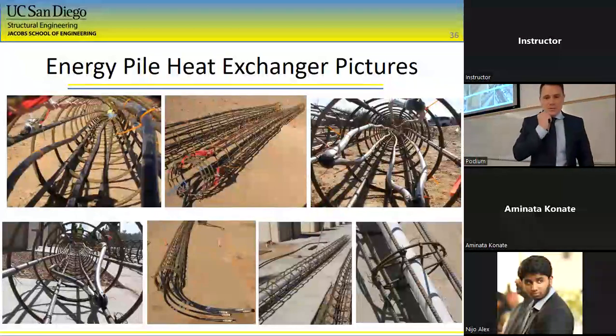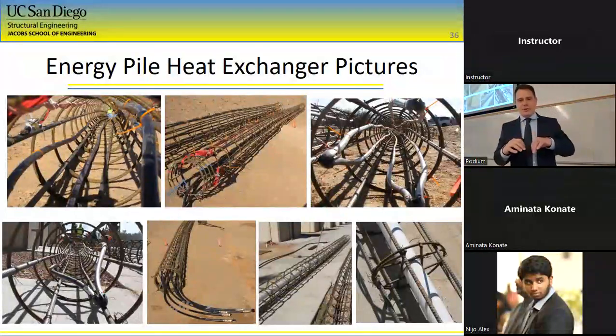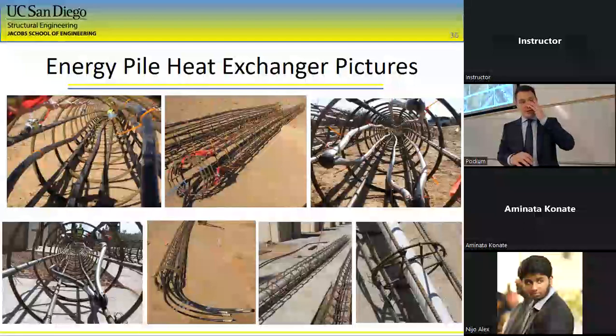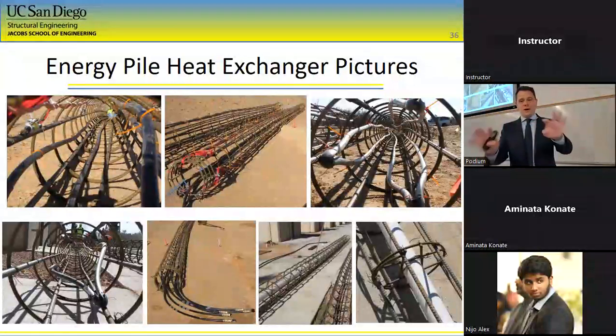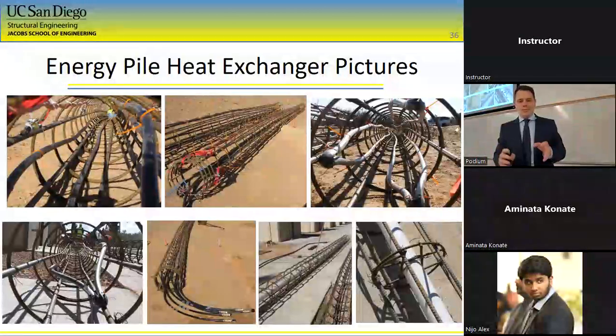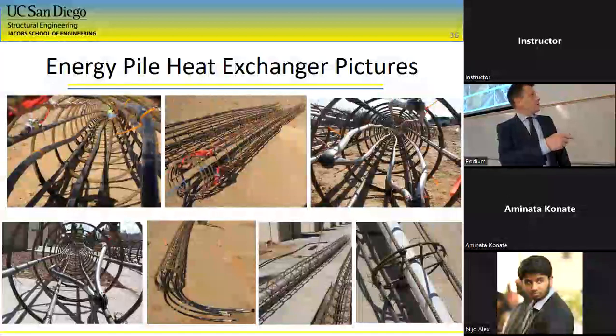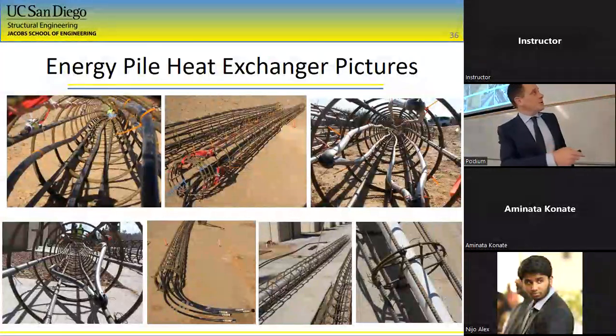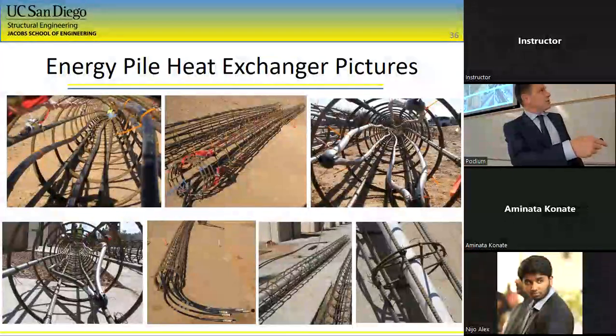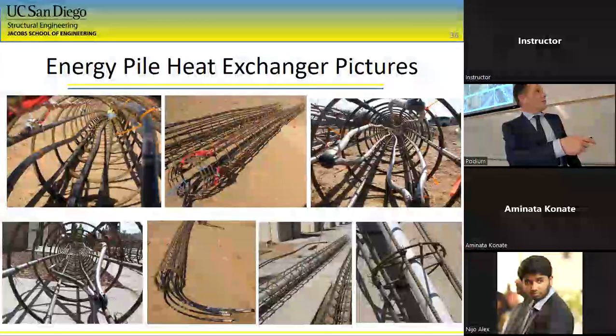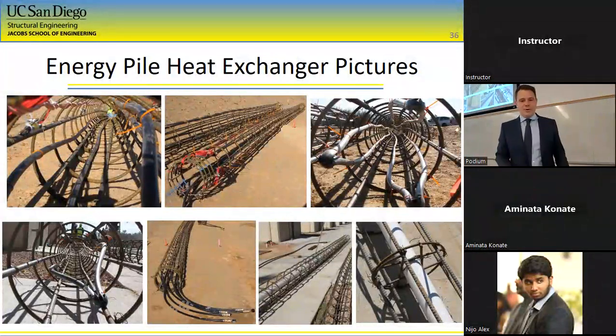Here's a couple of pictures of these energy piles. You always want to put the heat exchangers on the inside of the pile so that you make sure you have adequate cover between the sides of the hole and the rebar. And we always want to try our best to keep the pipes separated, as you can see here, because the cold or hot water is going to be flowing down one side and then coming back colder. You don't want to have a thermal short circuit between the pipes. So you want to keep them farther apart.